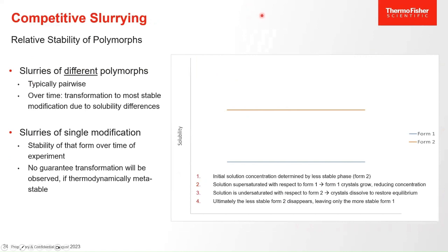And what is competitive slurrying? There are different ways of carrying out slurrying experiments, but the competitive slurrying is always a slurry of two solids, each in saturated solutions that are stirred together, typically pairwise, but you can do competitive slurrying with 3 or more forms if you want to. And over time, the system transforms to the most stable modification due to solubility differences.